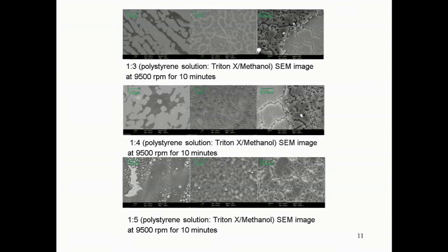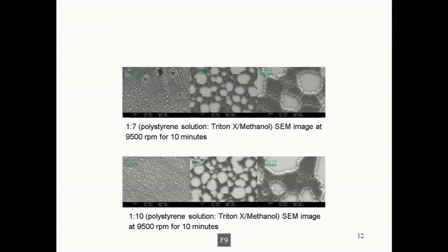Here, with solutions of 1/3, 1/4, and 1/5 proportion, there were bilayer and monolayer structures formed together, while having more than one uncoated area. With 1/7 and 1/10, the monolayers were formed together well, but the uncoated areas were far too large due to overspeed of the coating.